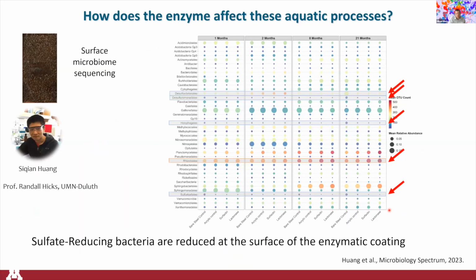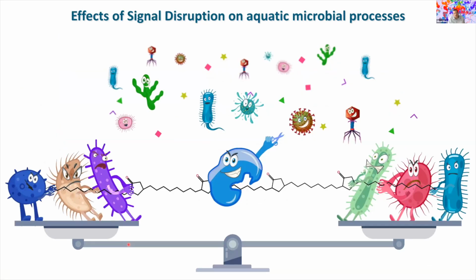So in this work, we actually showed that the presence of the enzyme changed the community that was present at the surface, and in particular reduced the abundance of these sulfate-reducing bacteria, and that was consistent with the reduction of biocorrosion that was observed there. So this is one way that we think the enzyme alters these biological processes such as biocorrosion and biofouling, by altering the surface microbiome population. So in a way, we think that this surface microbiome is in equilibrium. And these bacteria are all coexisting. They're communicating with each other with these different signaling molecules. And all of this is some sort of balance.